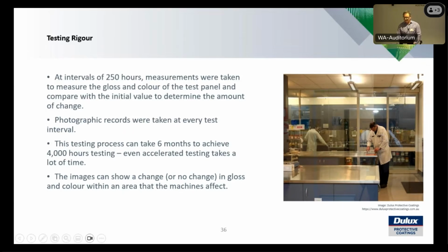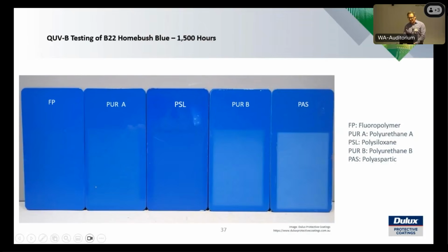But the images show in the testing I'm about to show with some of the pictures is variations in change in colour and gloss you'll find. Might be hard to pick up the gloss changes, but you'll be able to see the colour changes. So these photos were also presented by Rob, but so you got the fluoropolymer after 1500 hours. It's still, with the QUVB testing, it's still looking relatively new, you could say. Polyaspartic at the end, starting to show some signs of some colour chalking. The other, the PURA, the polyurethane A and the polysiloxane, no real dramatic effect, like not something you'd probably pick up with your eye, but if you're comparing it back to the starting point, then you would find some change.